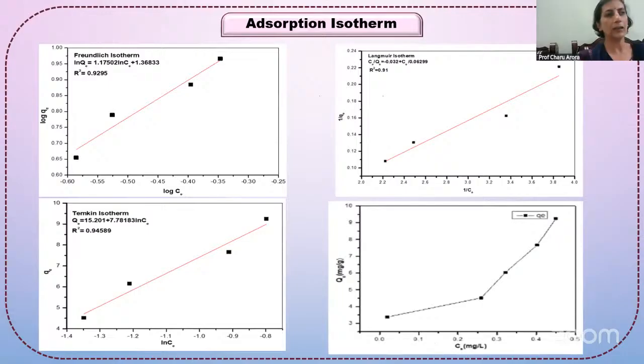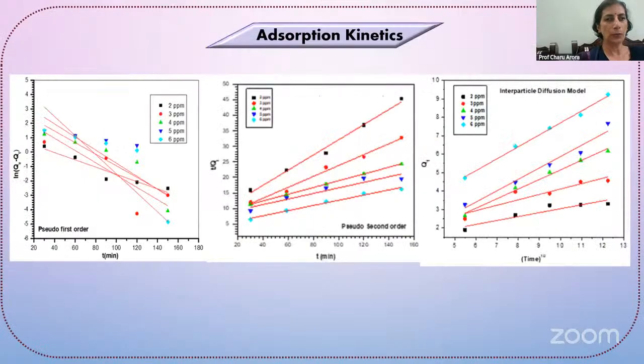Then adsorption isotherms were plotted. These are the Freundlich, Langmuir, and Temkin adsorption isotherms, showing that Temkin is the best fit because the value of the coefficient of correlation R square is maximum for Temkin. The value is 0.94589. These are the plots of adsorption kinetics, showing that intraparticle and pseudo-second order are the best fit.